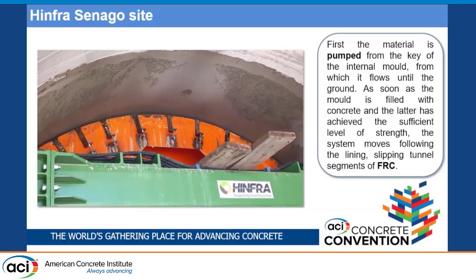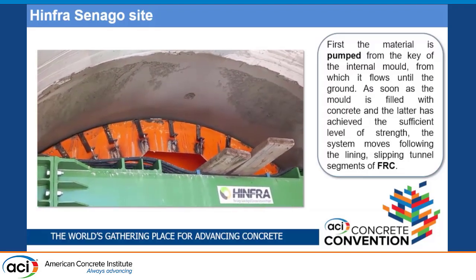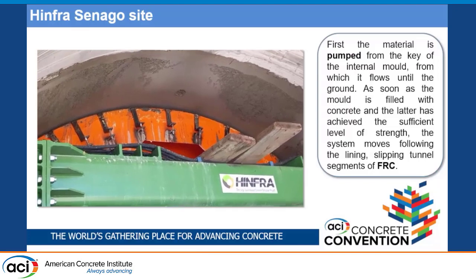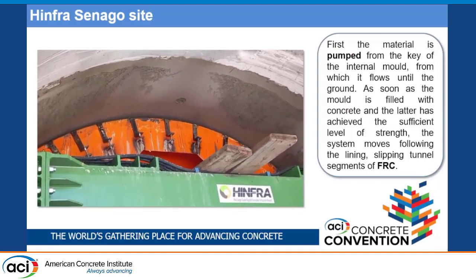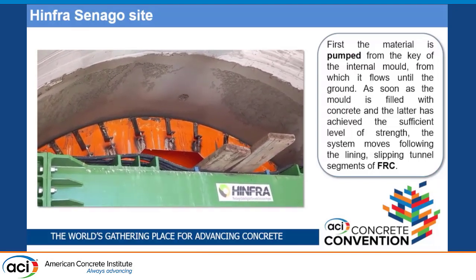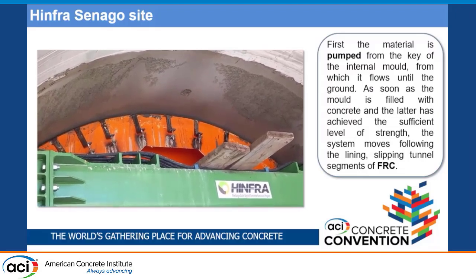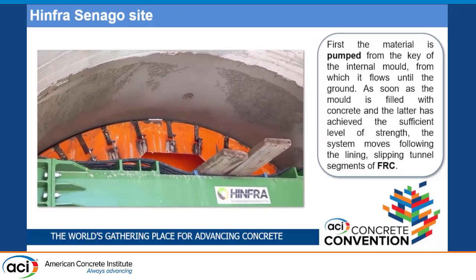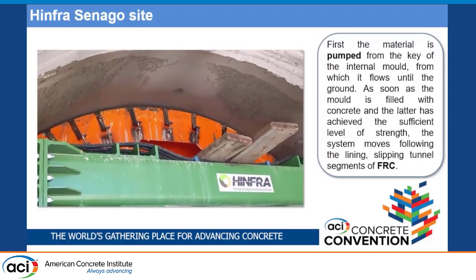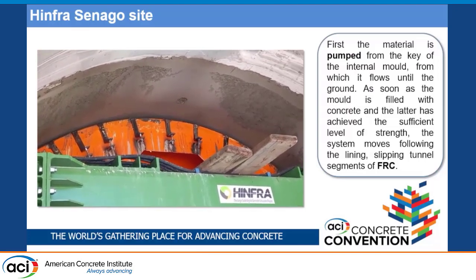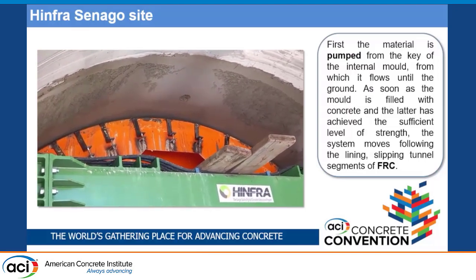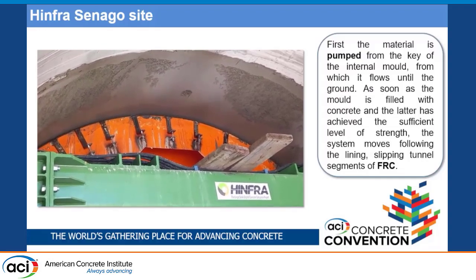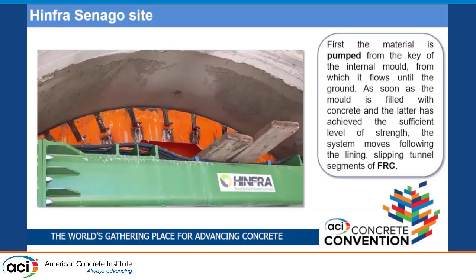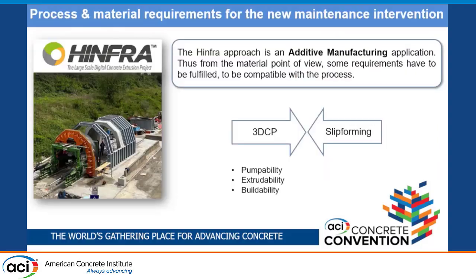So the velocity, the speed of the mold, it's more or less around 15 millimeters per second, so it's very fast. And the length of each segment is about 1 meter. That is due to also the capacity of the mixer that is not such high to build segments longer than 1 meter.